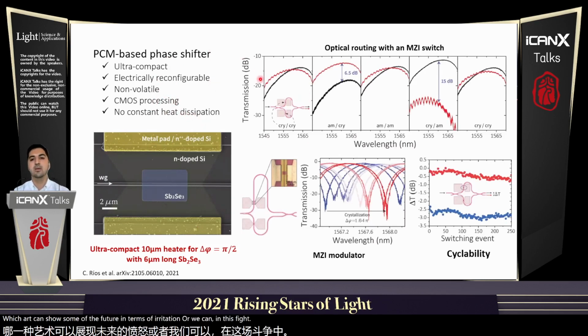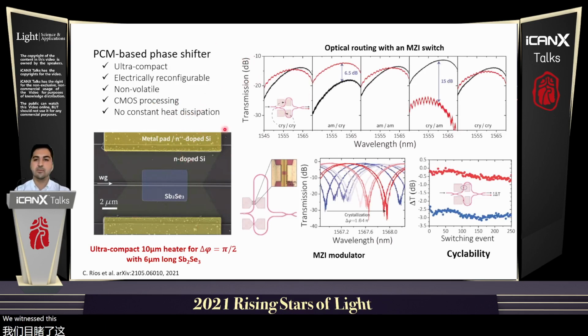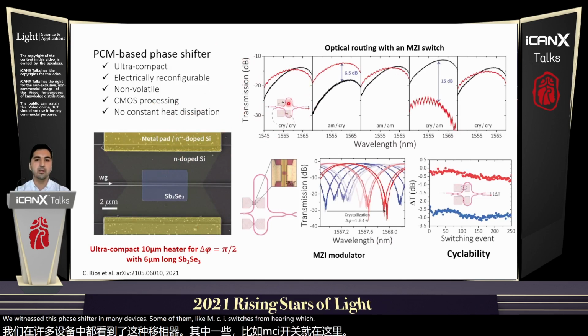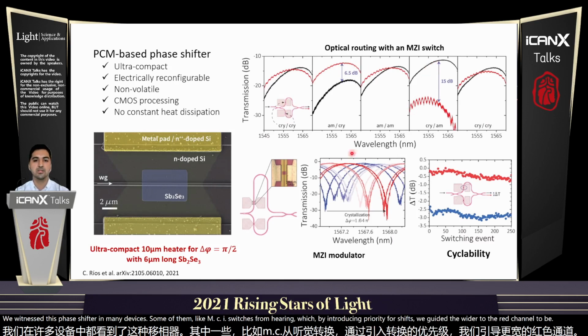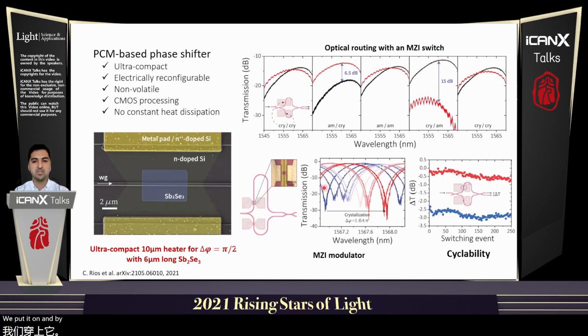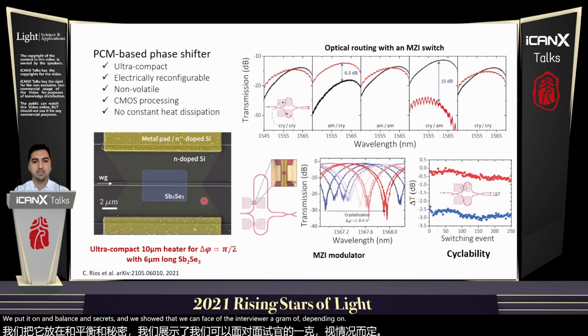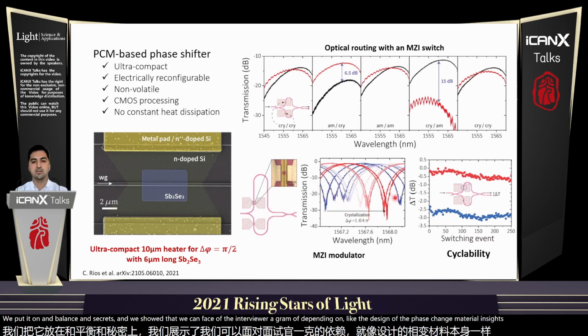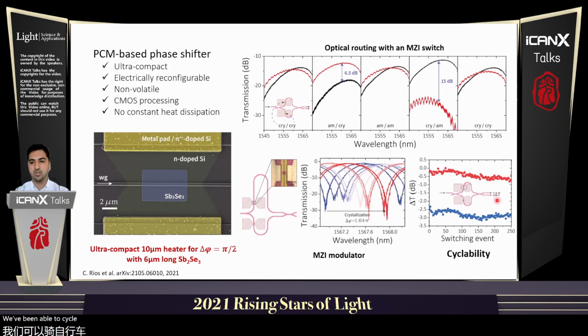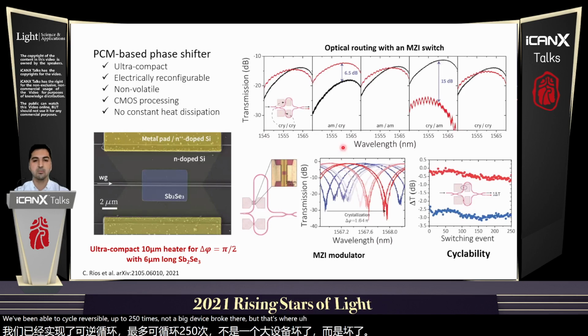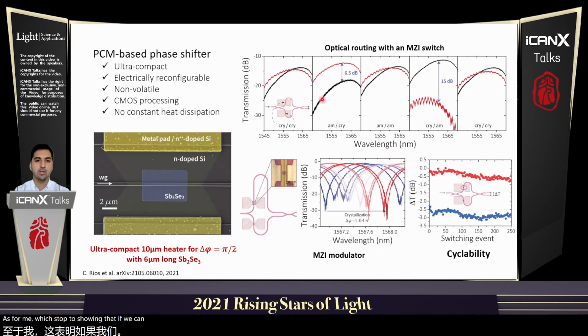We put this phase shifter in many devices, some of them like MZI switches here, in which by introducing pi/2 phase shifts, we guided the light either to the red channel or to the black channel. We put it on unbalanced MZIs, and we showed that we can phase shift the interferogram depending on the design of the phase change material, its size, etc. We've been able to cycle reversibly up to 250 times. Not that the device broke there, but that's where the experiment was stopped. So this shows that we can really reconfigure this device many times.